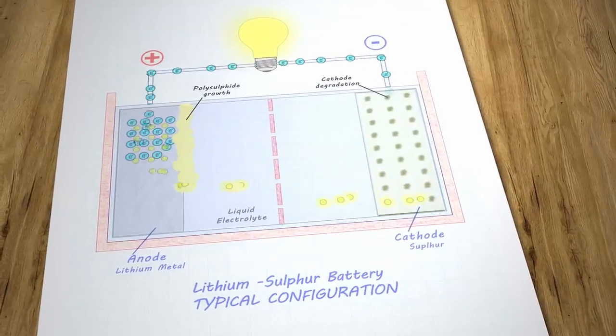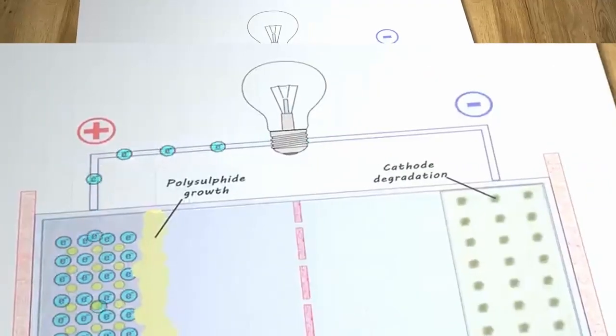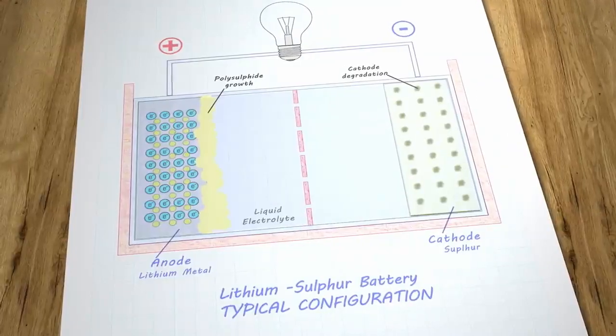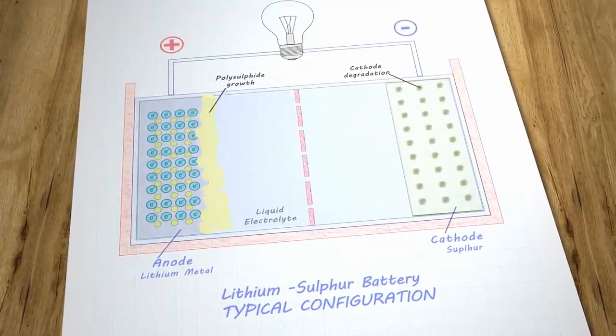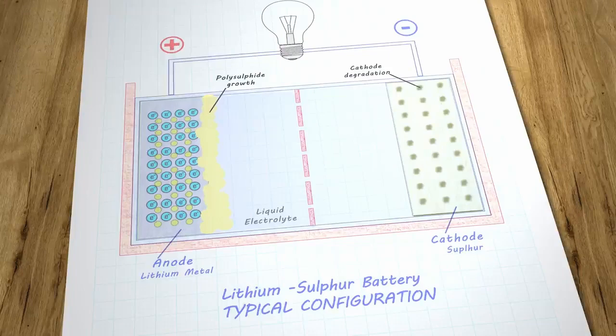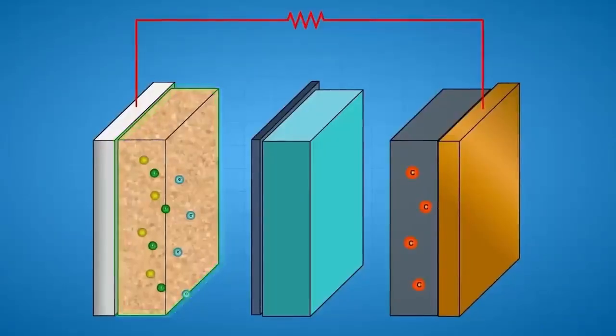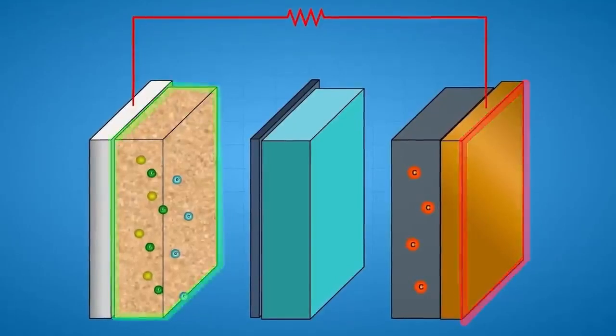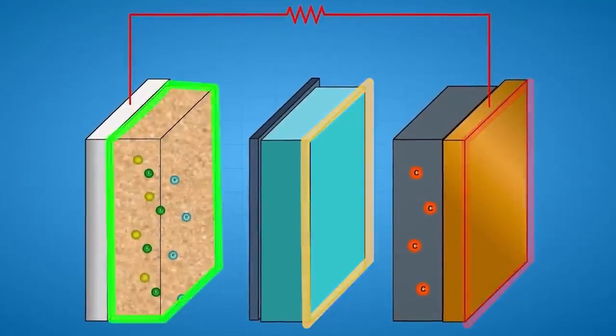This stage totally halts the process that generates polysulfides inside the battery. The battery was put through 4,000 charge cycles without losing capacity thanks to this technique, which means it lasts at least twice as long as lithium-ion. It's also important to note that their batteries could charge just as quickly and had three times the energy density of lithium-ion.